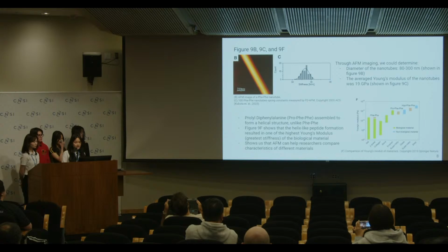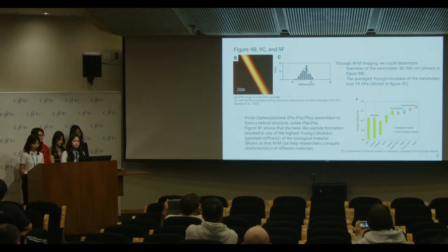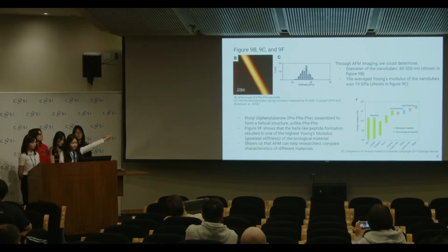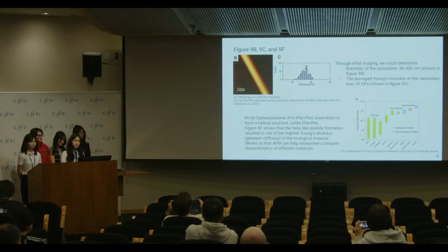These are parts of Figure 9. And as you can see from Figure 9b, which is right over there, the AFM helped us visualize the nanotubes, and through that, researchers figured out the diameter of the nanotubes, which is 80 to 300 nanometers. Figure C shows a histogram of the nanotubes, right over there, and allowed the researchers to visualize the distribution of data regarding stiffness. Through this, they found that the average Young's modulus of the nanotubes was 19 gigapascals.